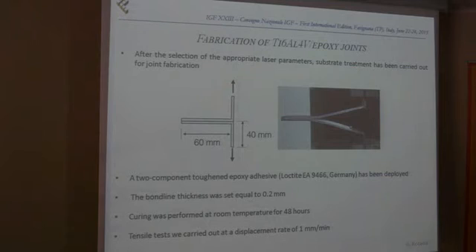We did that because usually when you perform a T-peel test, you are able to measure the absorbed energy, so the dissipated energy during the debonding process, which is important to understand if the joint really has an improvement in its behavior. And we compared the results with the baseline, so the as received material, which was degreased before bonding.